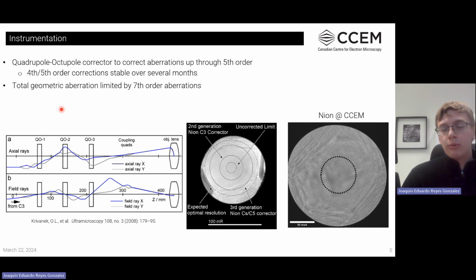This is very important when we're working at the lower accelerating voltages especially, because these are going to get distorted very, very easily. 30 kV, 60 kV, 100 kV, which our scope is aligned at, any small amount of distortion in your probe is going to make it very difficult to do analysis there. This corrector specifically is allowing us to really do some high-end analysis at these kVs.